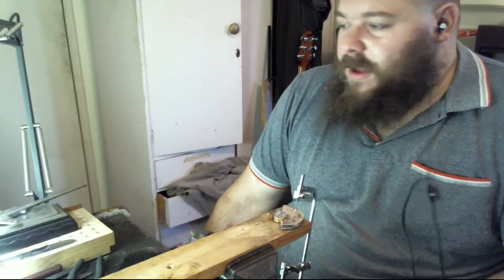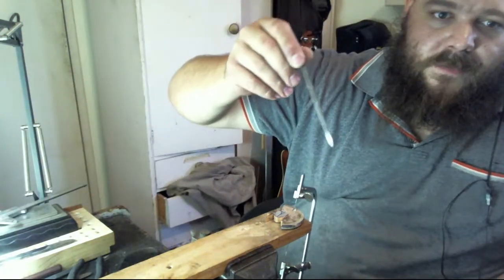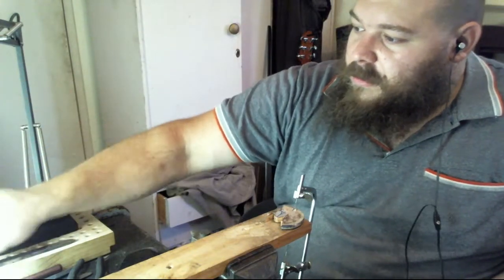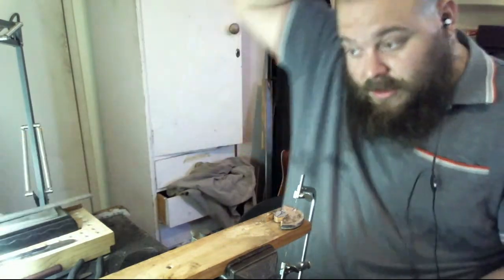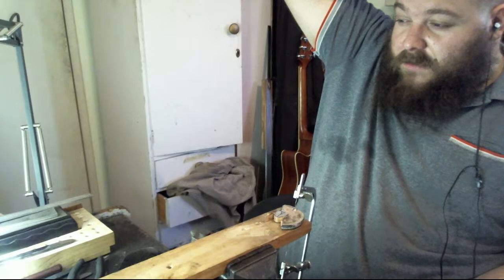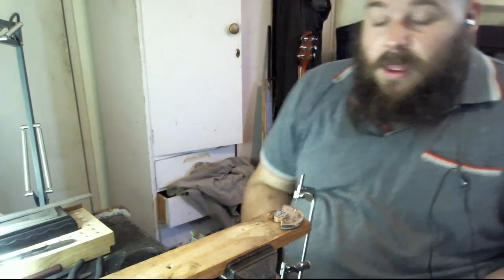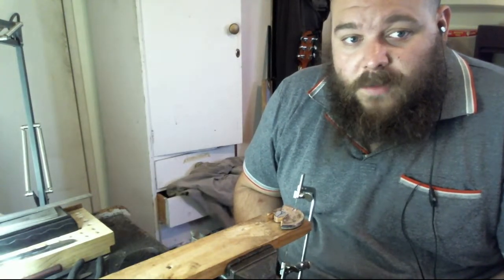What steel for engraving tools? So you can use old files, like from this scribe. It's just an old triangle file. A lot of my engraving tools are old files, but you can also use... I recently started forging them out of... Recently started using 1084 for a lot of my work, and 1095 and W2. The Japanese prefer W2.